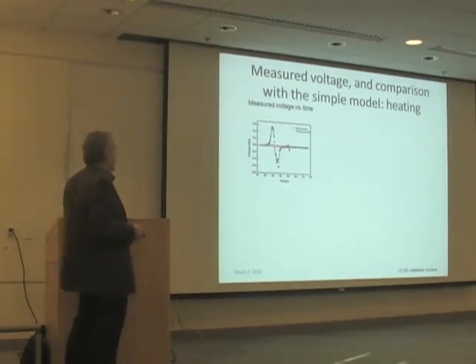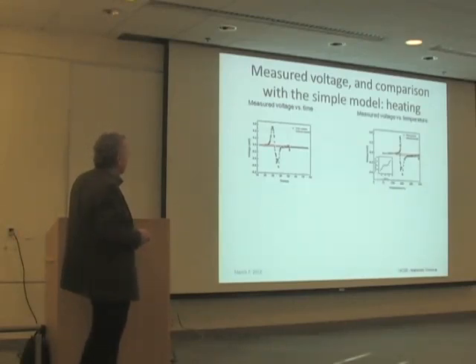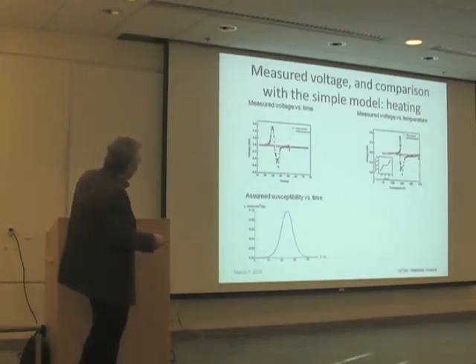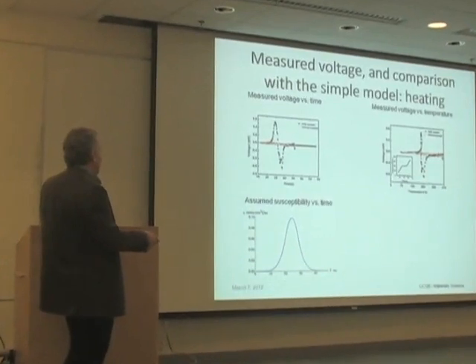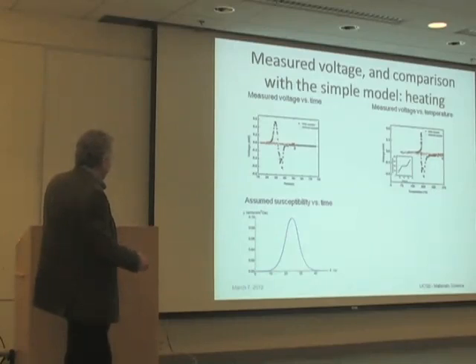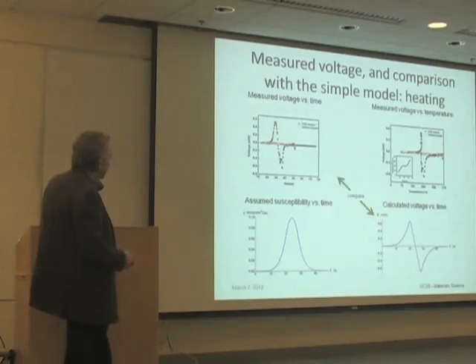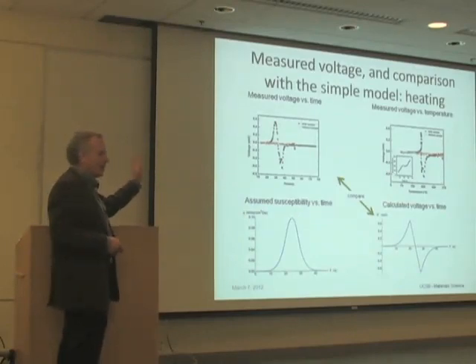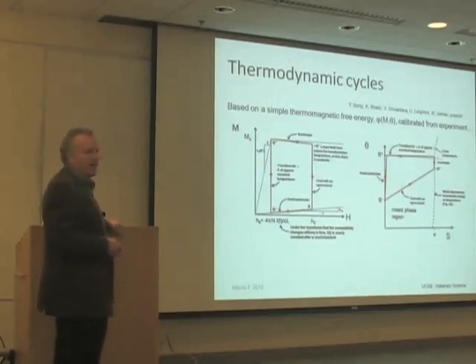There's voltage versus temperature. It's slightly stranger because, due to the latent heat absorption, there's a little non-monotonicity of the temperature versus time. So when you eliminate time between these two, you get this little, anyway, it's not important. We took, from the measured data, susceptibility versus time, and we calculated voltage versus time. And you can see even a simple model does quite well. So this design, I'm not claiming anything about this design. This design is very bad. But it does indicate a possible way to convert heat to electricity, and you have no generator. The material does the work.